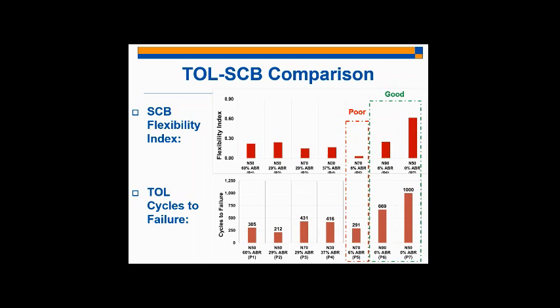So who knows? Maybe if you tested at very low temperature, -12 degrees Celsius, at a very slow loading rate, which would simulate a higher temperature, you would get similar results to our 25 degrees Celsius. So what we're doing here is we're not taking anything for granted. We're not assuming that the current classic SCB testing setup is accurate. We're also examining that, which is why I'm saying it wouldn't necessarily be the thing to compare to. You see what I'm saying?